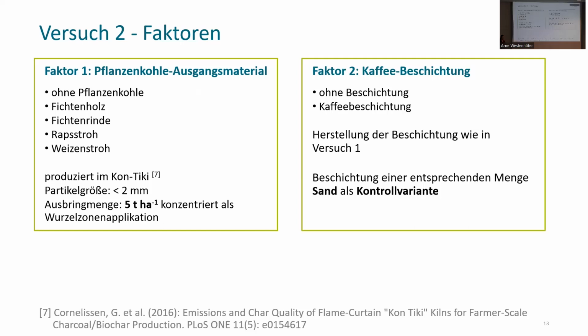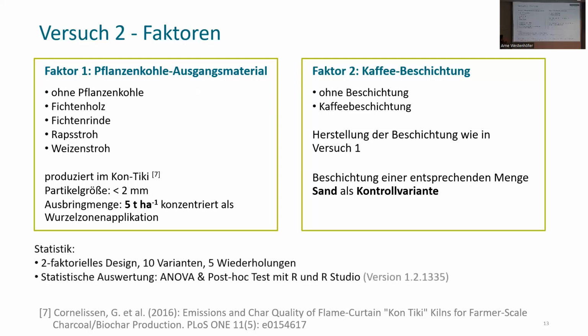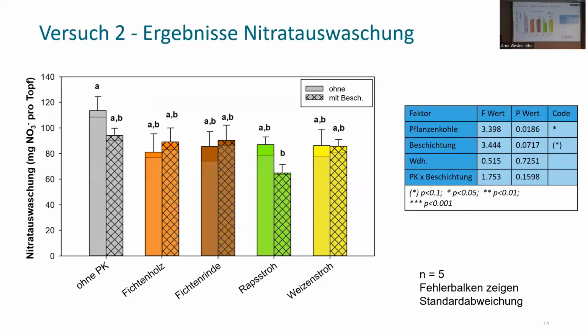And in order to have a real control variant, I use sand to coat it with the coffee to be able to compare, is it because of the coating? Does the coating have an effect, or do we also need the biochar to produce an effect? Two-factor design, as I said, 10 variants, 5 repetitions of each variant, with a variance analysis that we carried out to produce the analysis.